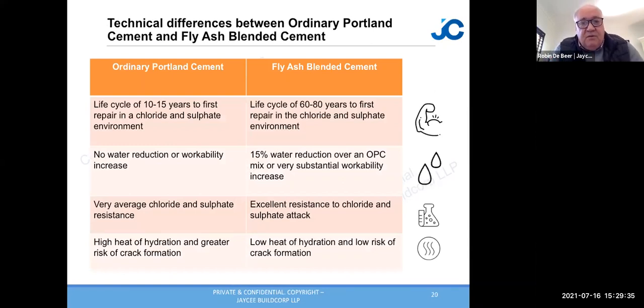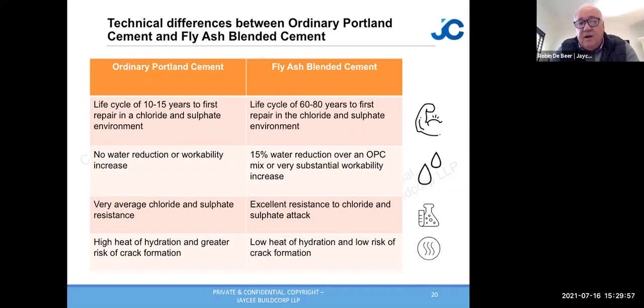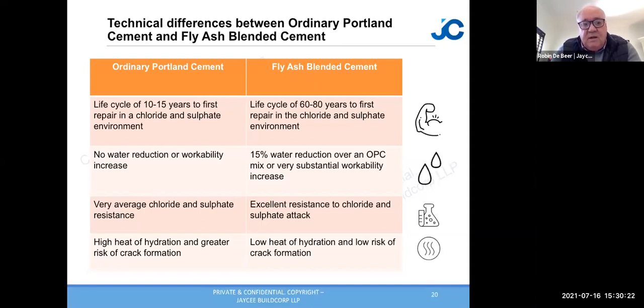Comparing OPC to fly ash blended cement: OPC gives a life cycle of about 10 to 15 years before the first cracking problems, whereas fly ash gives up to six to eight times that durability. OPC often requires more water depending on grinding fineness, while fly ash gives a 10-15 percent water reduction. OPC is average against chloride and sulfate attack, while fly ash is excellent for both, and fly ash significantly reduces heat of hydration cracking risk.